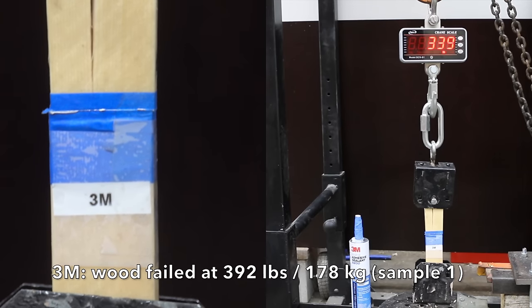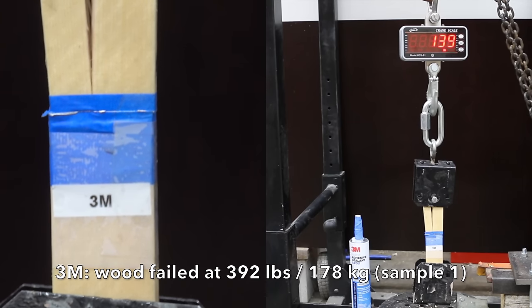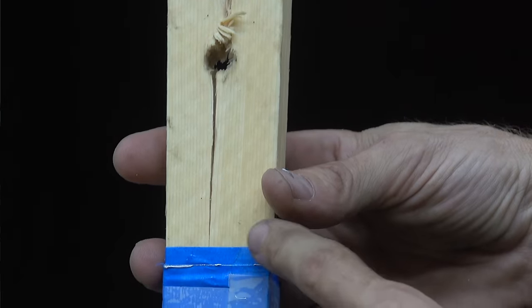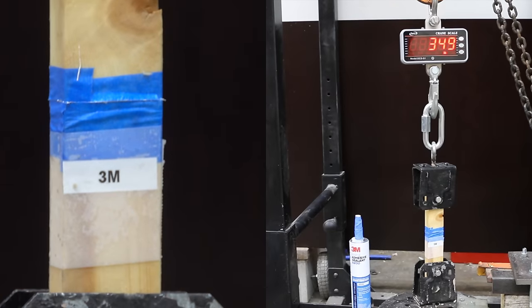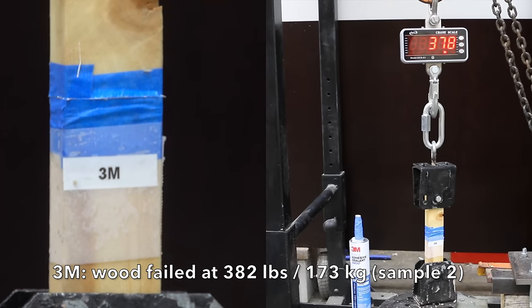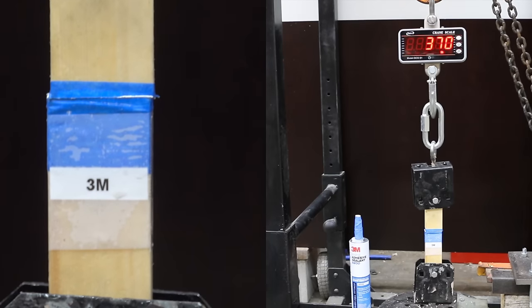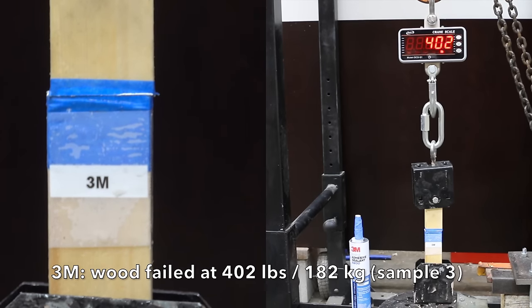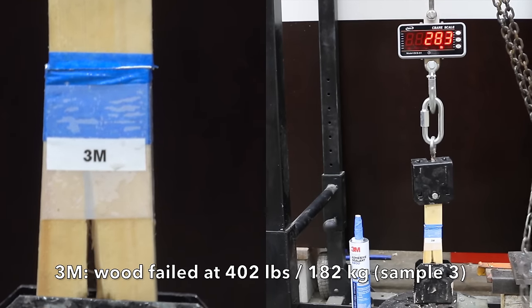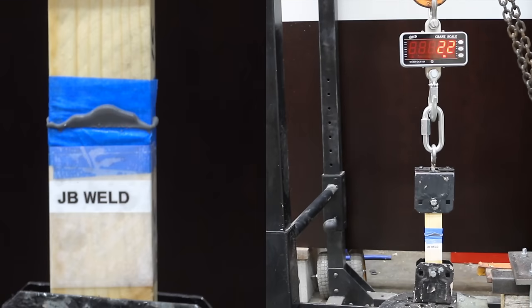Let's see if 3M can handle the water exposure. The first was the best yet at 392, but the wood failed, not 3M. The second was down slightly to 349, but still very good. The third is the best yet at 402 pounds, but once again the wood failed, so 3M is the only product tested so far that seems to be unaffected by the water exposure.